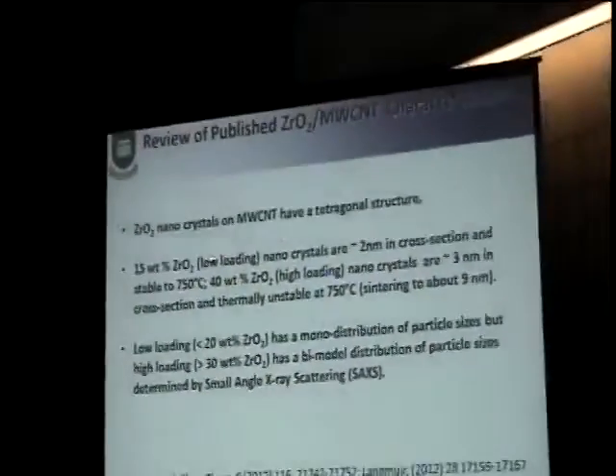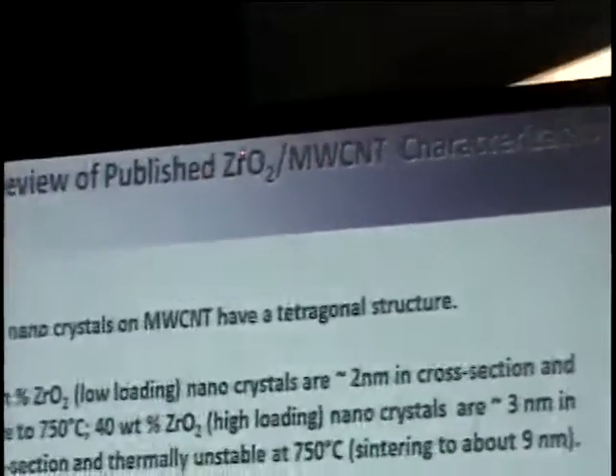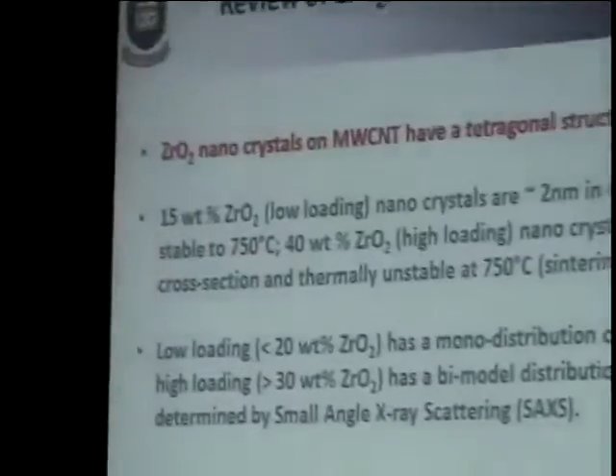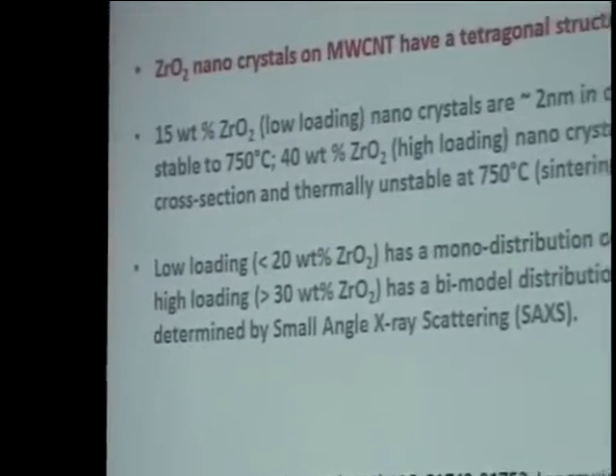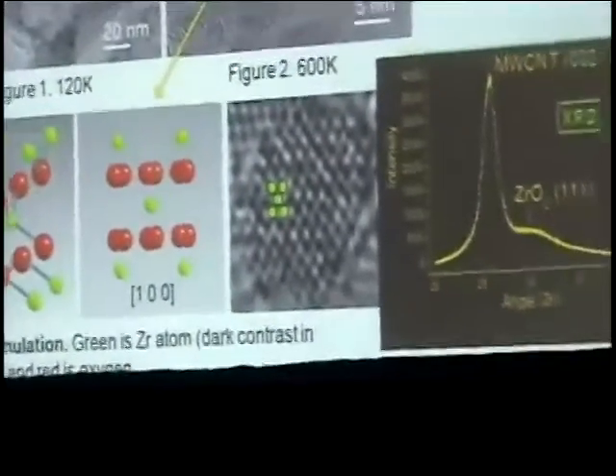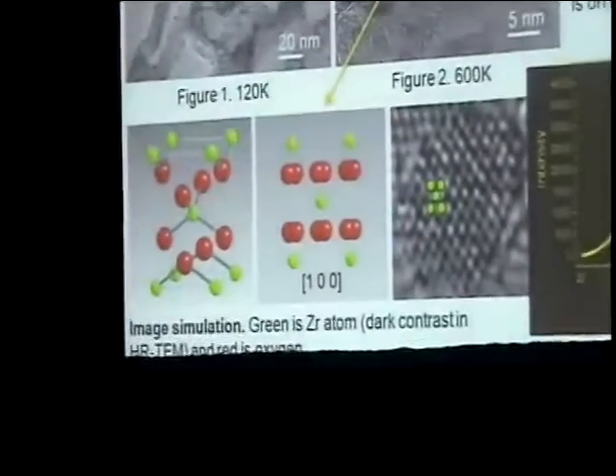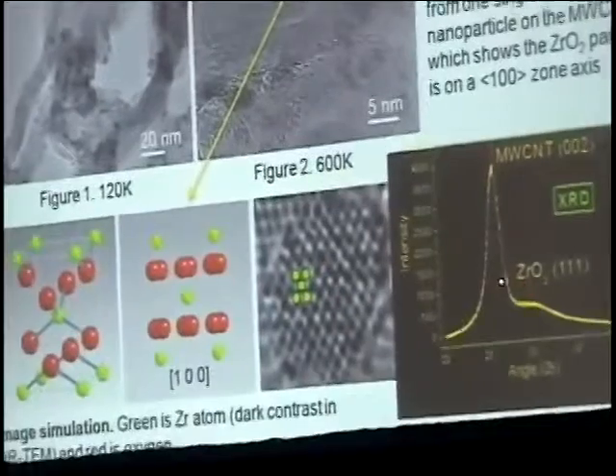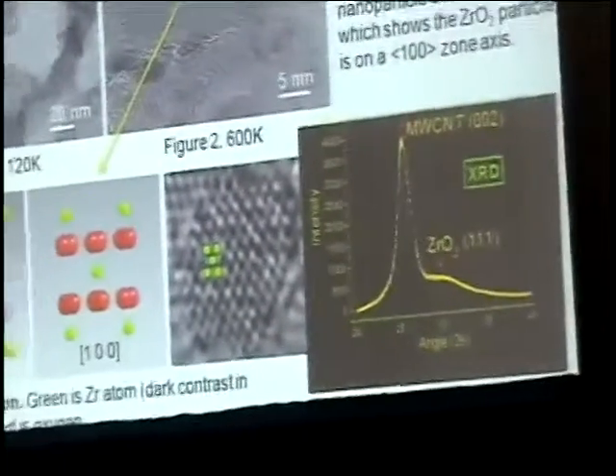So we have been working on the problem for some time. There are 2 recent papers that have been published, and I just want to quickly review the background of just the support, which is the zirconium oxide nanoparticles on carbon tubes on which the sulfate is going to be put. So the first thing is that the zirconia nanocrystals are tetragonal in structure. This is something that Burt looked at, the fact that sulfate will stabilize the tetragonal structure. How do we know it's tetragonal? High resolution TEM, where there's a single particle there. Here's a blow up of that single particle, and here's a model of it. There's a fast Fourier transform that indexes as the tetragonal structure, and if we look at it by ordinary X-ray diffraction, we can also identify that the phase is tetragonal zirconia.